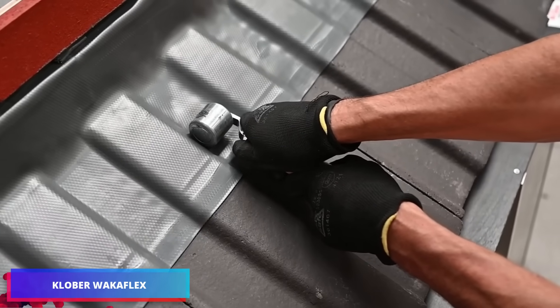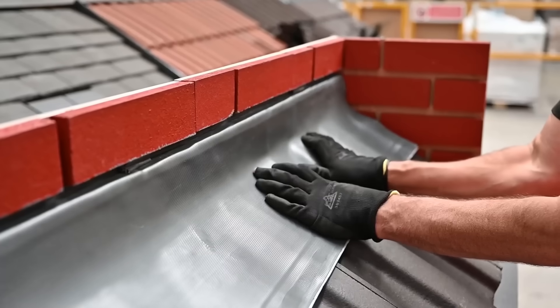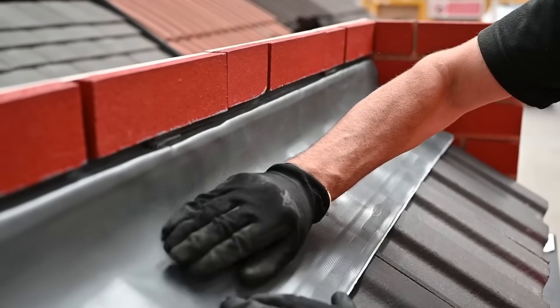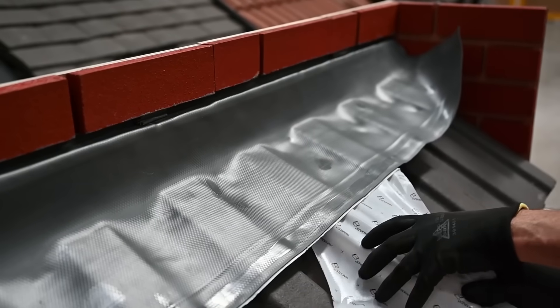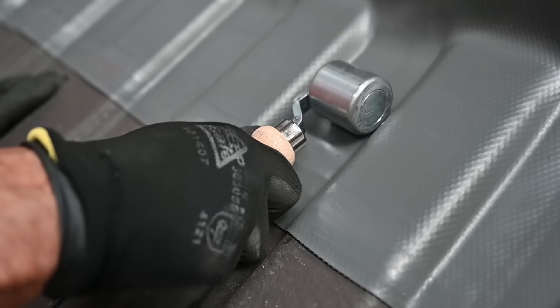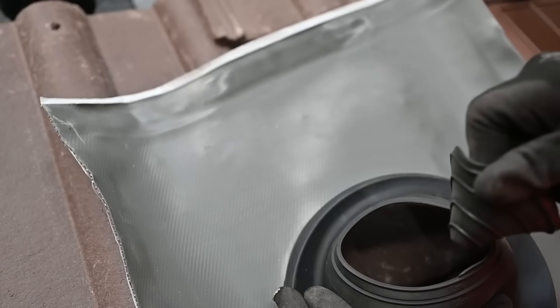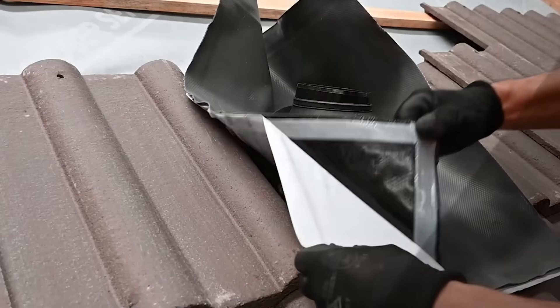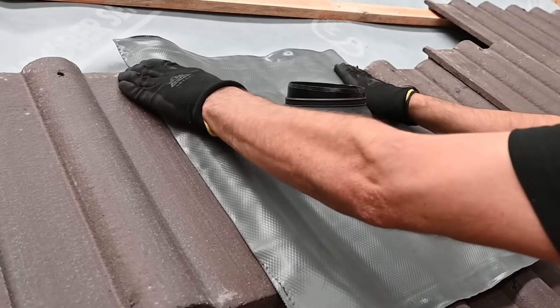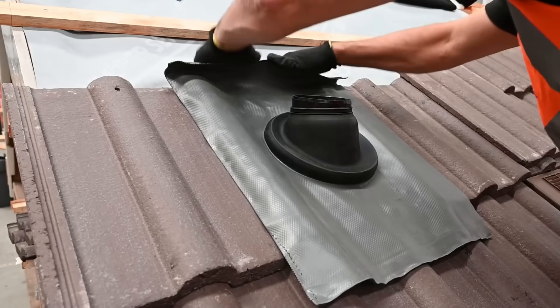Wakaflex is a versatile waterproofing tape that molds seamlessly to intricate surfaces. It's crucial for installations around bay windows, skylights, and chimney structures. Wakaflex consists of an aluminum mesh integrated into polyisobutylene featuring adhesive bands on both sides. The product expands 15% width-wise and 50% length-wise. It's compatible with virtually all roofing components, ranging from ceramic tiles to metal sheeting, and requires no special equipment — only scissors, a measuring tape, a roller, and competent hands.